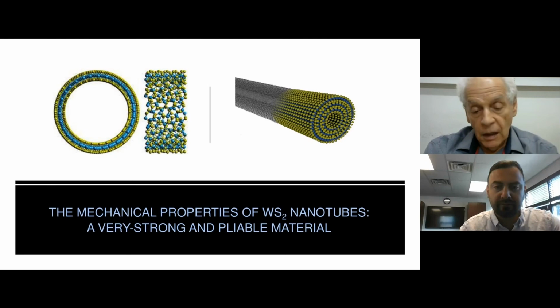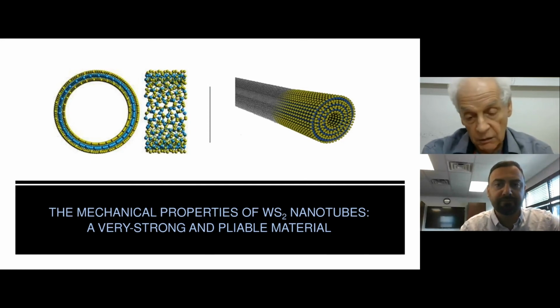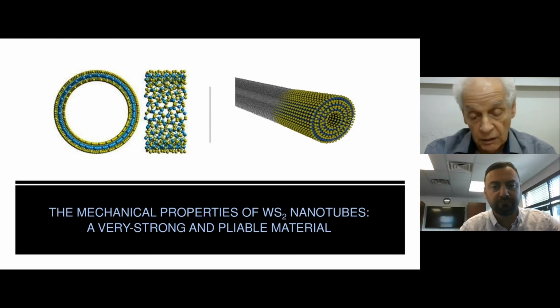But in an anaerobic atmosphere, namely in a polymer or another matrix like metal or ceramic, you can heat them above 1000 degrees C and nothing will happen to them if they don't react chemically with the matrix itself. We have shown this already mixing them with magnesium and aluminum melts, and we saw similar effects to those with polymers.